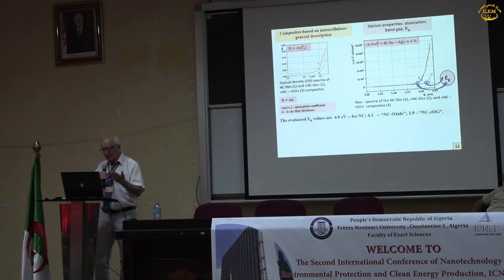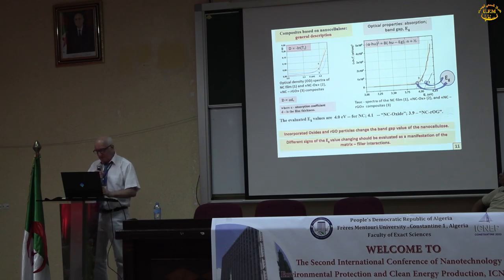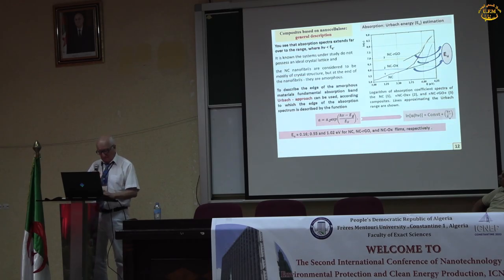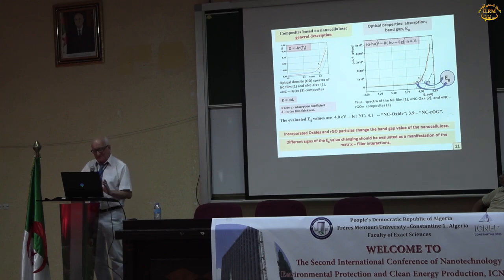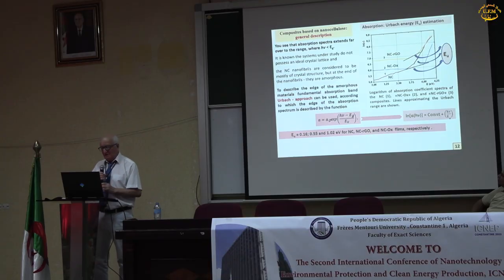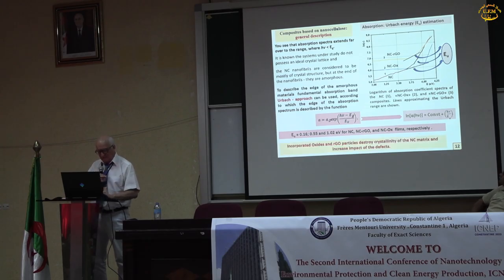Based on this data, we can evaluate the band gap of the components and of the composite, and we see that the evaluated Eg changes compared with the matrix. Different signs of the Eg value changes should be evaluated as a manifestation of matrix-filler interactions. Also, we evaluated the end of the absorption using the so-called Urbach approach, and we see that there are many defects and destroyed components of these molecules. So we concluded that incorporated oxides and particles of carbon nanomaterials destroy the crystallinity of the nanocellulose matrix and increase the impact of the defects.